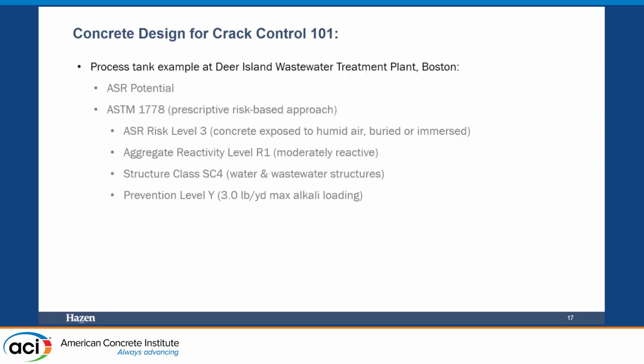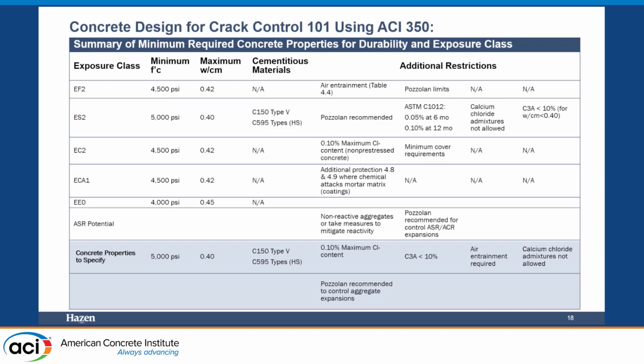You should also consider the potential for ASR for our type structures. We're often assuming a risk level 3 with an aggregate reactivity level R1. Water and wastewater structures would have a structure class of SC4, which would give us a prevention level Y with a requirement of 3 pounds per yard for maximum alkali loading for those givens. So you put all of that in a table and compare what you end up needing, and when you look at your controlling compressive strength and your controlling water cementitious materials ratio, we would find we would need a 5,000 psi concrete with a maximum water cement ratio of 0.4.